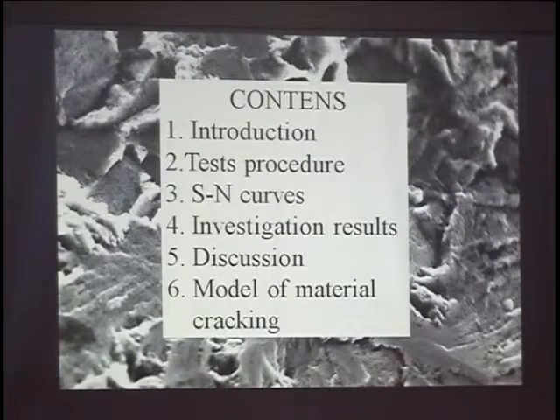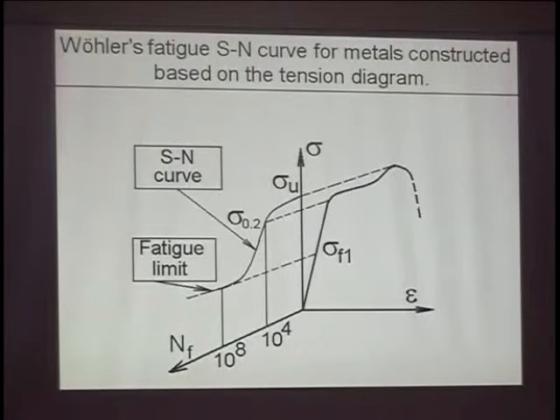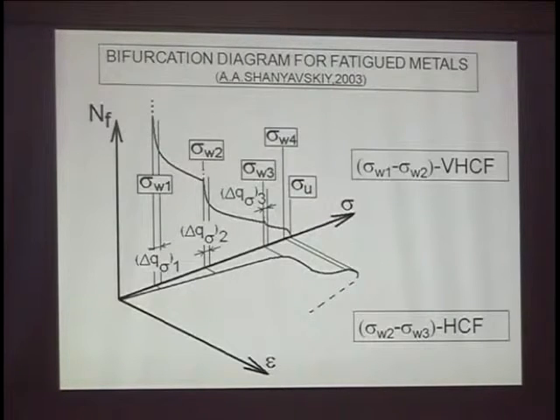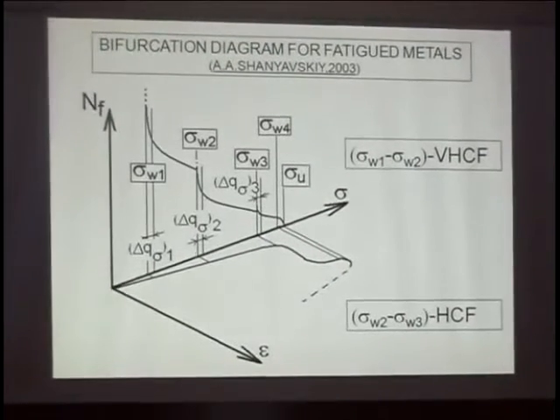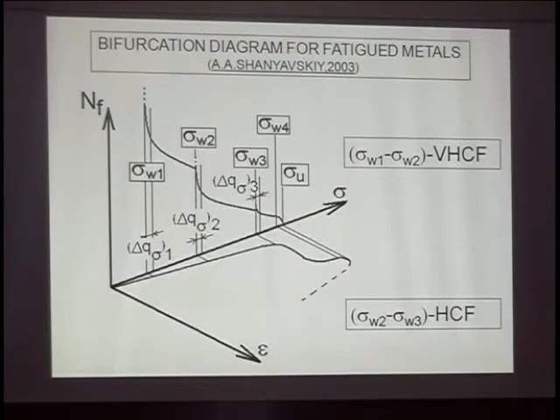It's a well-known situation, for instance, for the traditional S-N curve, the Wöhler curve. We would like to use a bifurcation diagram for step-by-step estimation of different areas of material cracking in the regimes of very high cycle fatigue, high cycle, low cycle fatigue and quasi-static fracture, and the border between transition from one region to another is a bifurcation area where two kinds of cracking of material can exist.